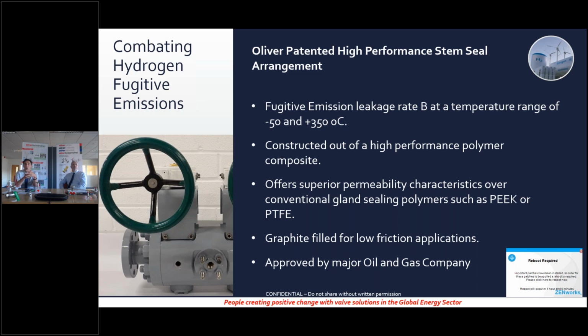So we worked very closely with DuPont and came up with our own high performance composite polymer that had very stable mechanical properties right the way through the temperature range of the project. So -50 to +350 degrees C. But this material was new to the oil and gas industry. It wasn't recognized by the end user. So there was a challenge in itself of not only qualifying the valve, but actually getting acceptance from the end user. So using our own in-house R&D facilities, we managed to demonstrate its performance through our own range of qualification tests and gained acceptance from the end user.